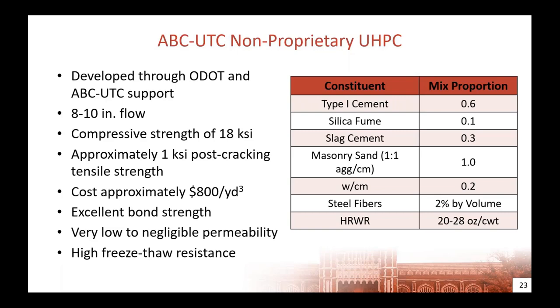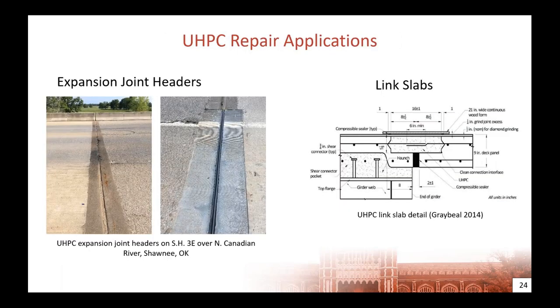And in addition to what Walt has mentioned already, there are a number of possible applications for UHPC repairs that we've examined at OU and that have been examined in the literature, including repair of expansion joints in the headers on either side of the expansion joint, replacing steel armoring with ultra-high performance concrete to have an impact-resistant material that can be ground to the profile of the bridge. Link slabs can be used to eliminate joints and create a continuous deck, but still allow for simply supported behavior.